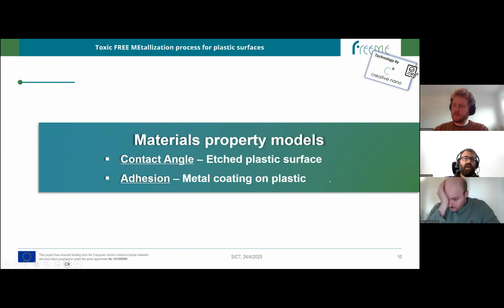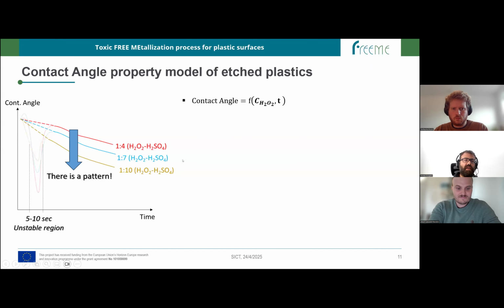And here come the two property models. The one main property model refers to the contact angle, which is actually a metric of how well a plastic surface has been etched. And secondly, we have also developed a property model to estimate the adhesion of the metal coating on the plastic substrate. So here come some models. Here you can see a graph where we have the contact angle versus the time of the etching process, right? And here you can see the different lines for the different Piranha solutions. And definitely we have identified that there is a pattern.